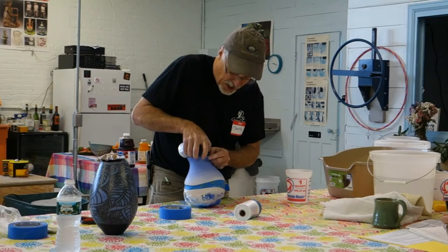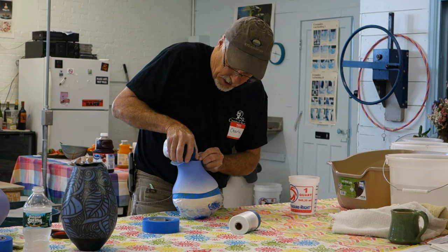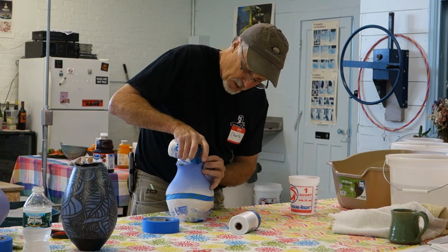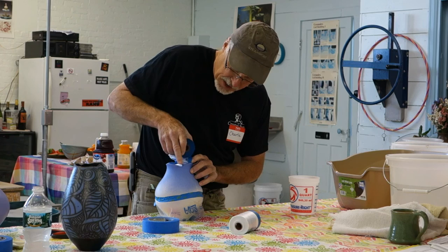The pot I'm working on here — I put the standard-color terra sigillata all over it, and then sprayed on with an airbrush some sigillata that was mixed with a tablespoon of a mason stain per cup of sigillata. So the standard thickness of terra sigillata that you'd apply to the pot, you would add one tablespoon of mason stain.